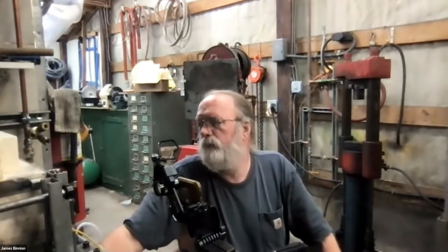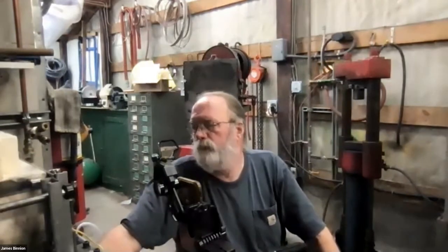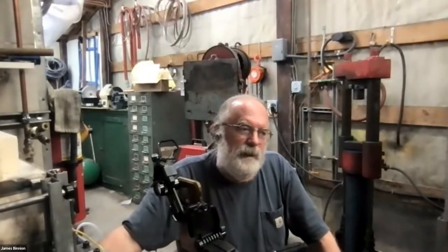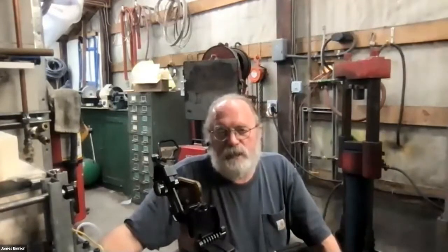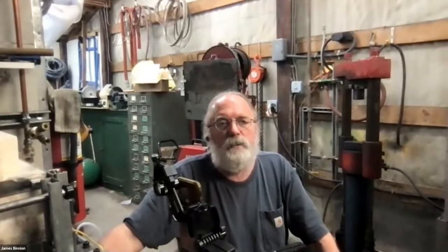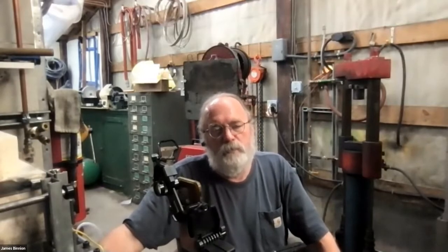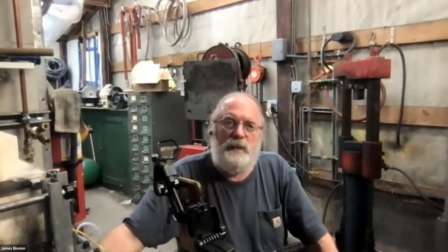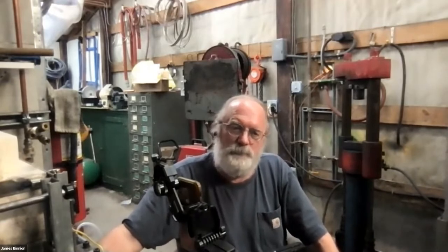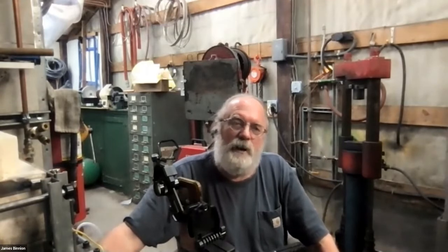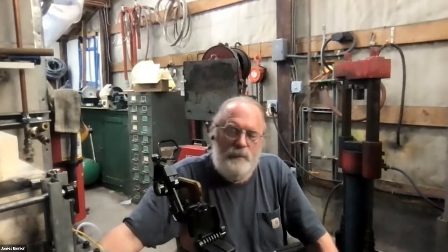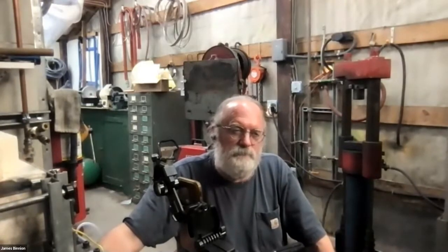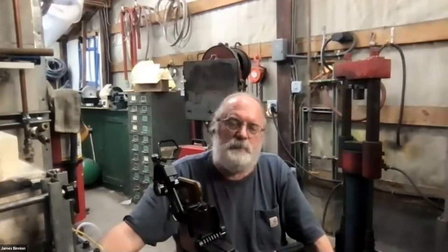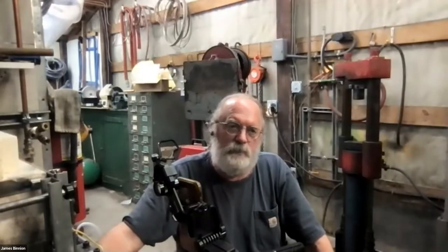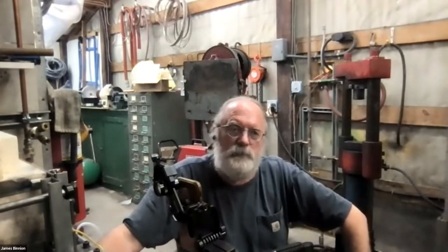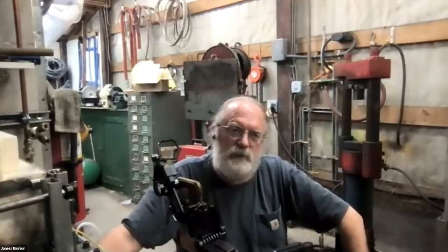Joe's asking if you've ever done a forge with a specific atmosphere, like injected with argon. Oh yeah. I did a whole series of experiments where I built a can around the billet and tried doing it in vacuum, doing it with argon flowing through it, doing it with argon with 4% hydrogen flowing through it. And my experimental results were, it didn't make that much difference between firing it that way and firing it either using charcoal or, in this case, using the strongly reducing environment of the gas forge that I'm set up.